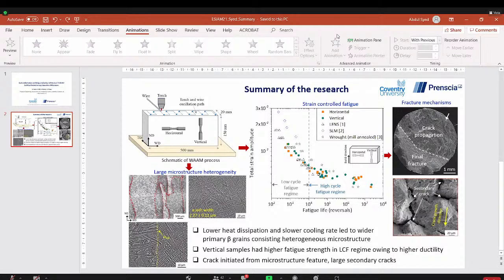Yeah, thank you very much, Professor Jürgen. We have built a number of walls using different deposition strategies using this technique. Because of the nature of this directed energy deposition AM process, as long as we are able to maintain good quality wire, I think we will be able to eliminate these defects. However, whenever we have used some low quality wire, we have seen some defects in the material, particularly gas porosity defects, that are mainly attributed to the quality of the wire.